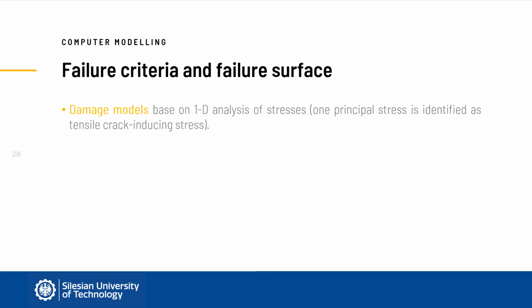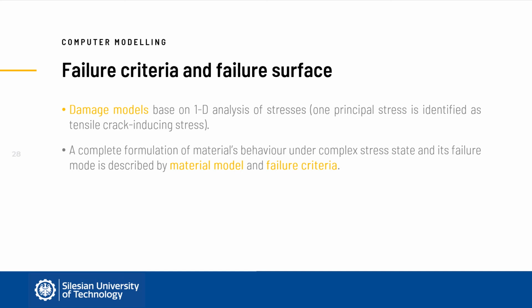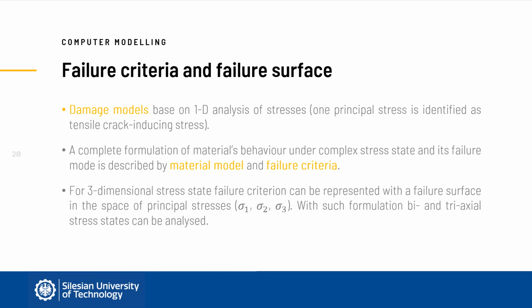Damage models are usually based on one-dimensional analysis of stresses. That is because in the elements analyzed with these approaches, there is one dominant principal stress which is tensile and which can cause cracking. However, some structural concrete elements undergo failure in complex stress states. Such complete definition of the material's behavior under any stress state is done with the material model and failure criterion. For a three-dimensional stress state, failure criterion can be represented with a failure surface in the space of principal stresses. Points on the surface represent stress states for which failure occurs.